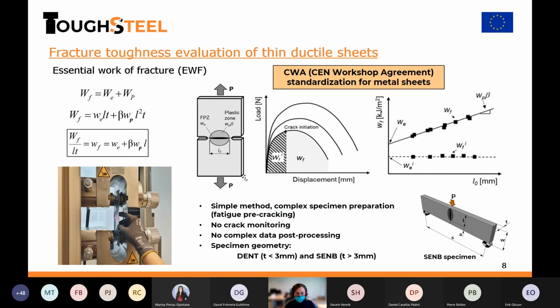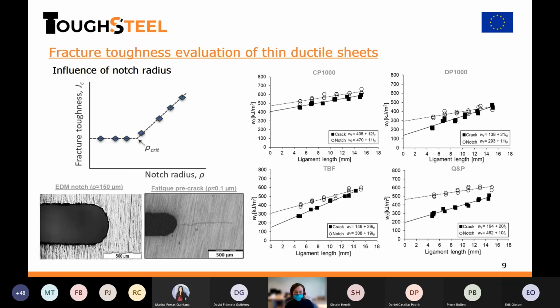preparing the specimens. They need to be with symmetric notches, and they need to be sharp. But that's one of the points that we will see here, that the notch radius for these specimens needs to be very sharp. And we can see here some effects, how the radius depends on the fracture toughness, and at a certain radius this can be well established. But if the notch radius is too large, we will have some dispersion on the results.